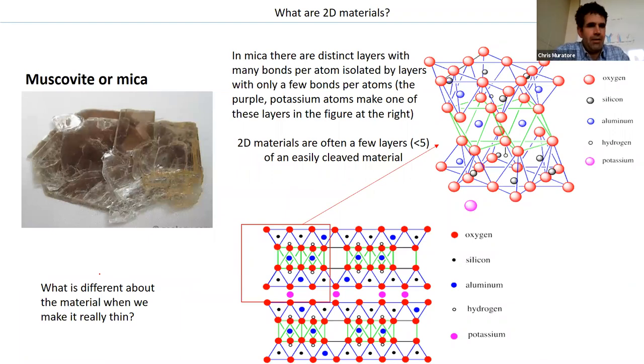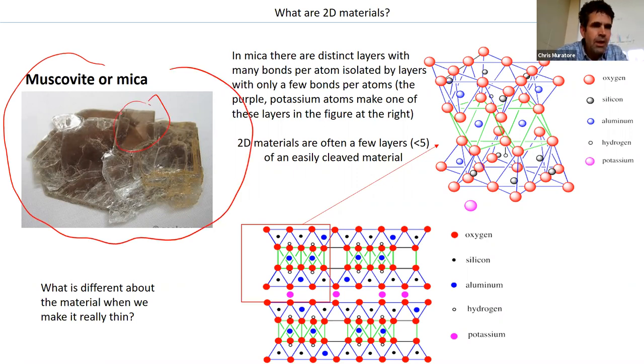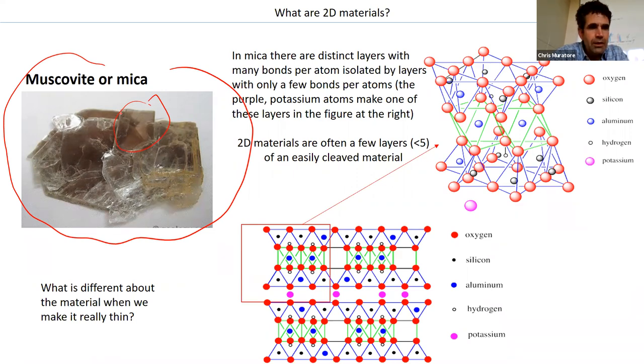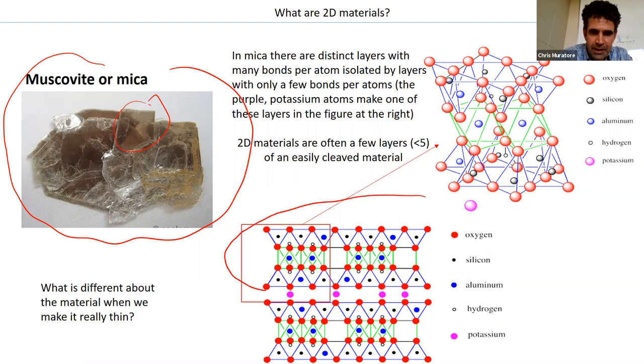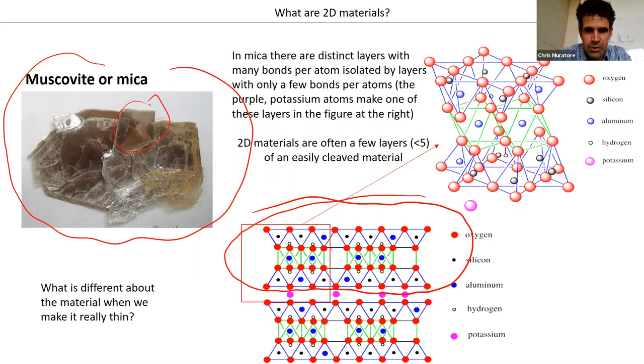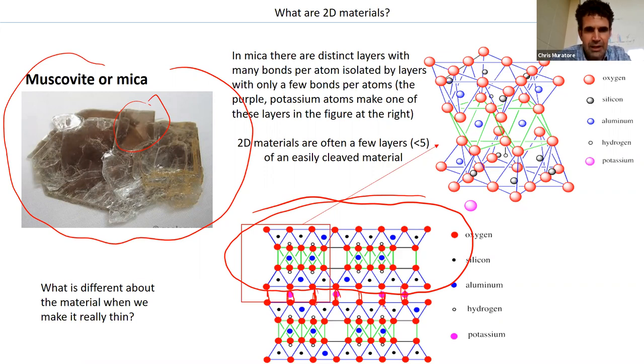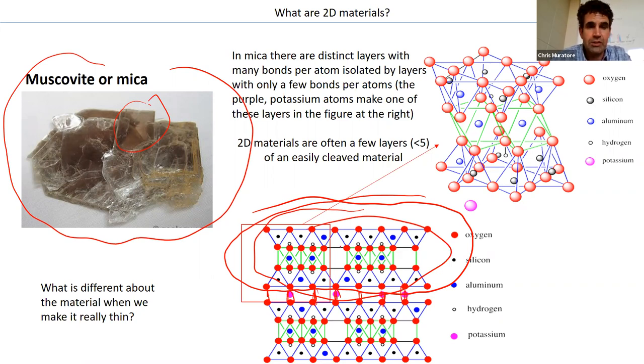If you take a layered material — this is a piece of mica — it's really easy to tear a sheet off. When you do that, you notice some big differences. The big chunk of mica itself, about a centimeter thick, you can't see through it and it's really rigid. But when you peel a layer off, each layer is made of strong covalently bound atoms, separated by weak Van der Waals forces. You can tear a layer off and it remains intact, but when thin it's super flexible and optically transparent.